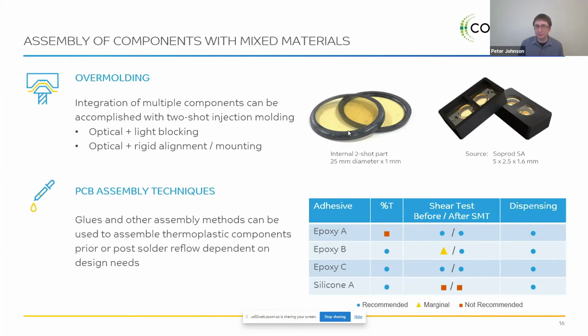And then the final thing was the PCB assembly techniques. We've done the epoxy and silicone testing. The few things to consider here is that if we're gluing, say, on this box on the outer edge, we really aren't super concerned with the transparency of the material. In the case of, say, when we're actually trying to glue the lens directly on the board, we might care about transparency, we might care about shear testing, or just the dispensing of it. So it really depends, but we've tried to sort of cover our bases in terms of what we need for assembling the materials out into the components themselves.